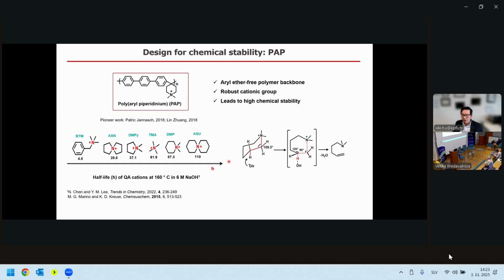One of the major decomposition pathways is the Hofmann elimination, which acts on the beta hydrogen, okay? You release it, and then you make a double bond. It turns out that such a transition state is typically quite rigid. However, if you make them into a cyclic structure, it's really difficult for them to reach the ideal transition state. And so you basically make it harder to do Hofmann elimination.